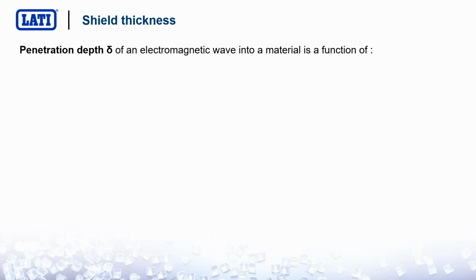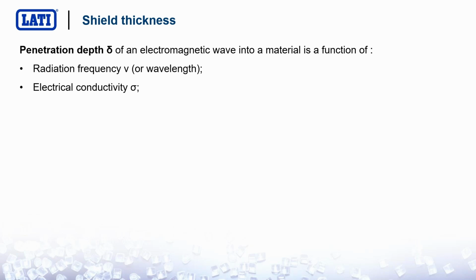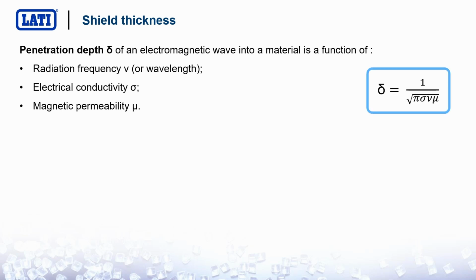How relevant is the thickness of the shield? A shield is more effective as the thickness grows, but why and how? In order to understand the penetration depth of the electromagnetic wave, we have to understand which factors are affecting it. The penetration depth is a function of the radio frequency, of the material conductivity, and the magnetic permeability of the shielding itself. The relationship is described like this, and we can see that the penetration depth of the radiation is higher for low frequency fields and for materials showing poor conductivity and poor magnetic permeability.